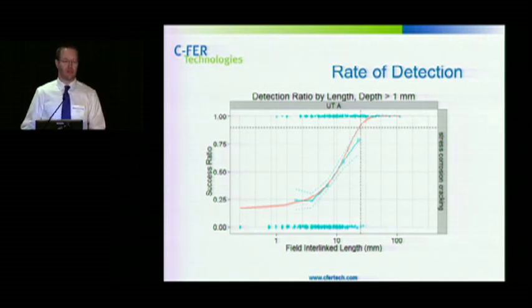That dotted crosshairs represents the tool spec, and you can see in this case that the data we found in the field shows that the tool met the specification. I think, as was mentioned previously as well, that the critical features are likely quite a bit to the right of that crosshairs. So this is referring to the vendor specification.